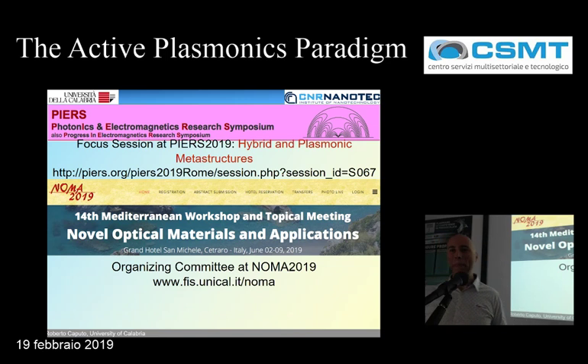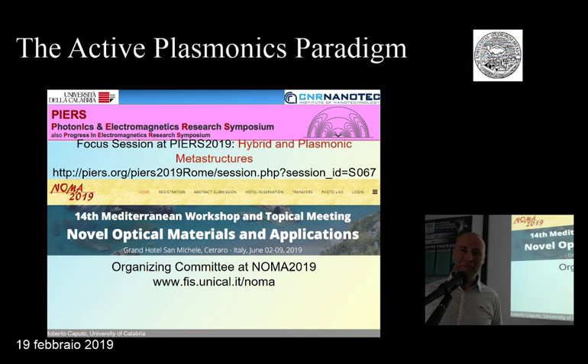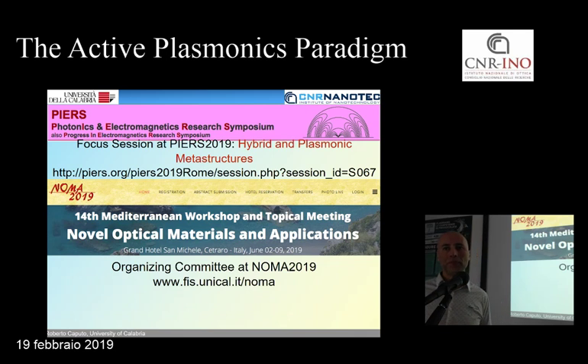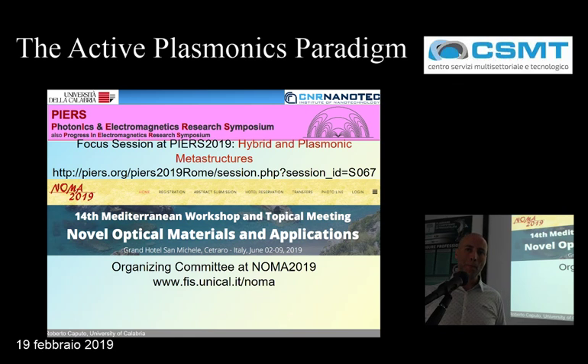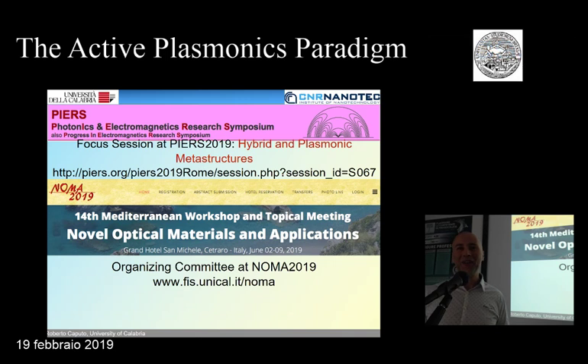Yeah, thank you for the interesting talk. I like it a lot. So far you've been monitoring the shift of the distance in your dimers mainly with the extinction perspective, so with linear properties, which depend on this distance, but not too much. Have you ever thought or tried to see if some nonlinear process, so for instance, you can look at the Raman signal of the polymer, which would be quite intense because there is a lot of CH bonds. So you see what I'm thinking?